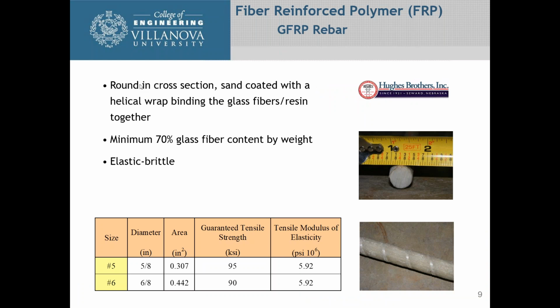Now, to just give you an idea what they are, they're round in cross section, and they sand coat them with helical wrap binding the glass fibers and resin together. In the bottom right hand corner, you can see what the helical wrap is. They are a minimum 70% glass fiber content by weight, and they're elastic and then brittle.